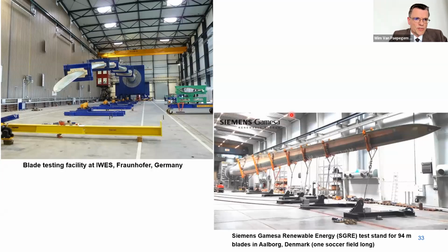These blades are tested in fatigue and also in static loading. Here you see a few pictures of certification tests where the blade is put under a certain angle, and then the blade is pulled downward with different cables to the ground. This can happen in edgewise, flapwise bending, and coupled loading to also have torsion. And you measure the reaction forces and moments. You also have stroboscopic measurements of deflection, strain gauges, and so on.